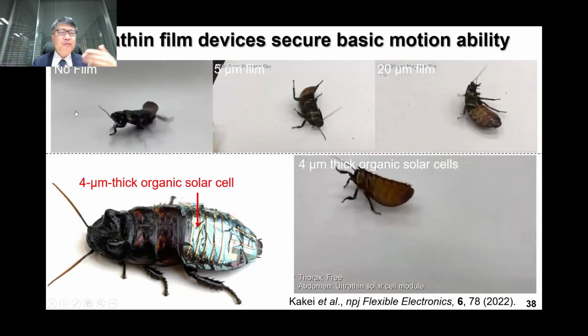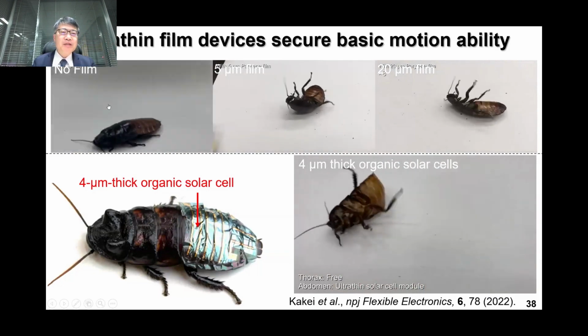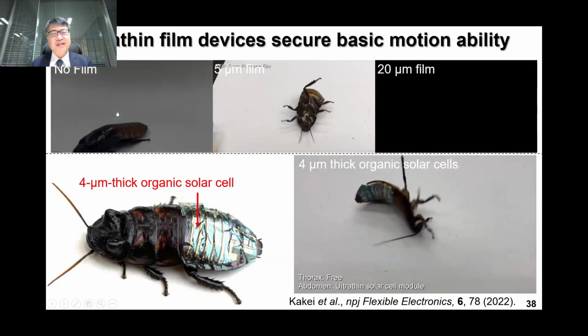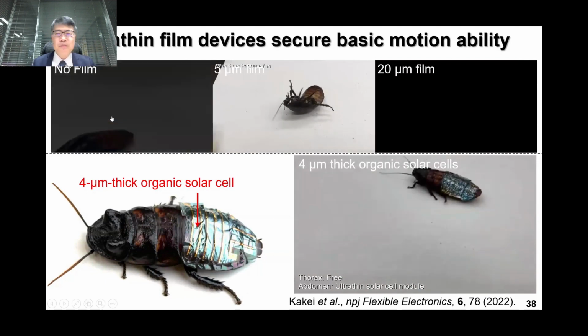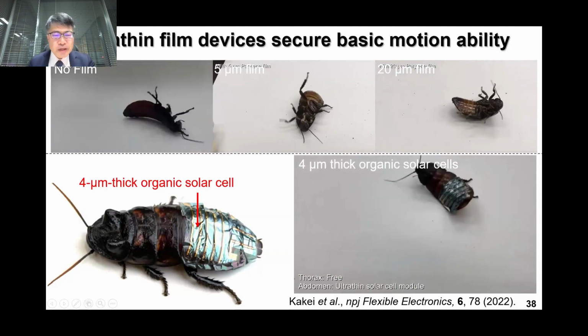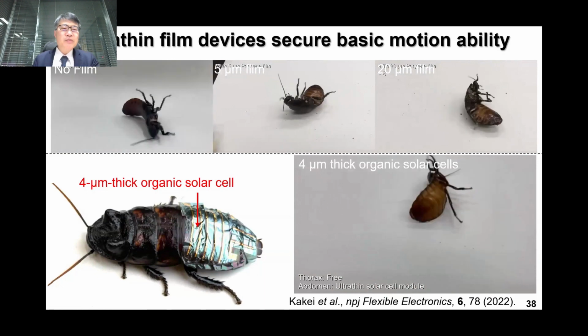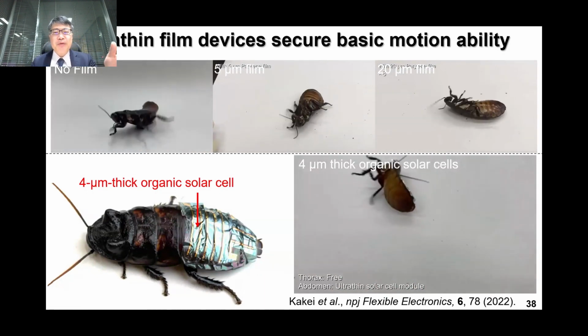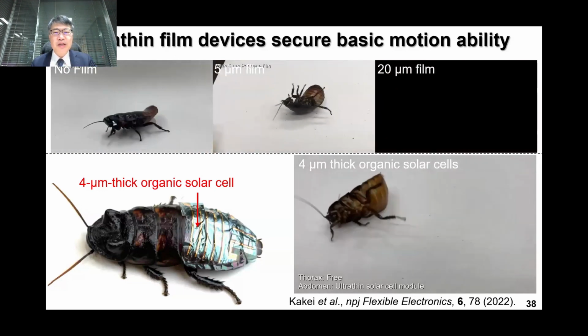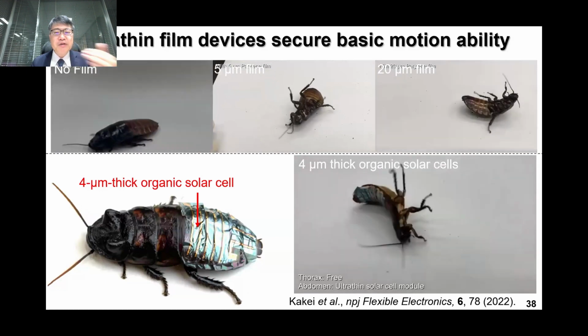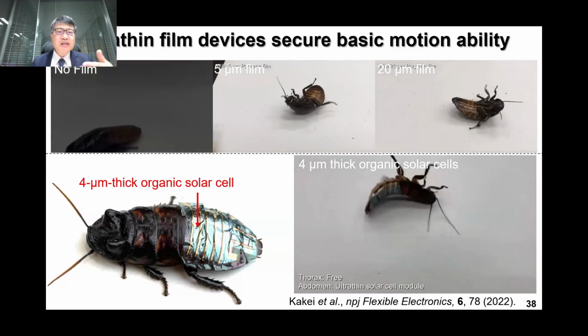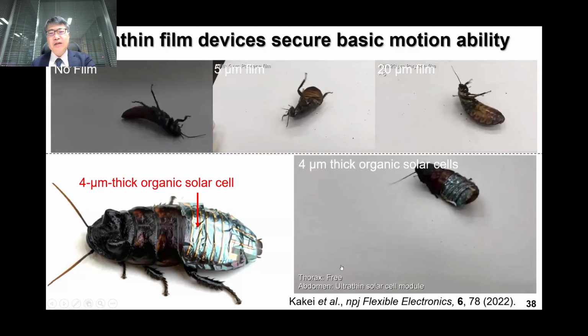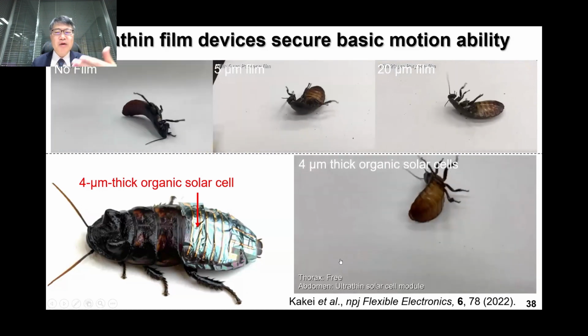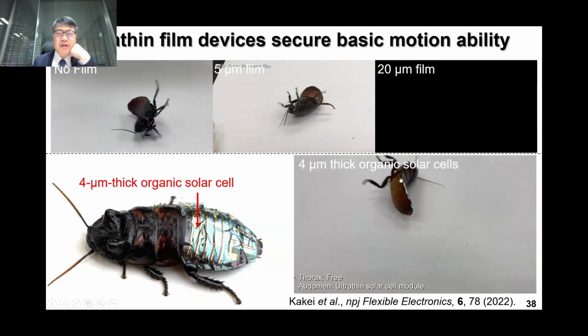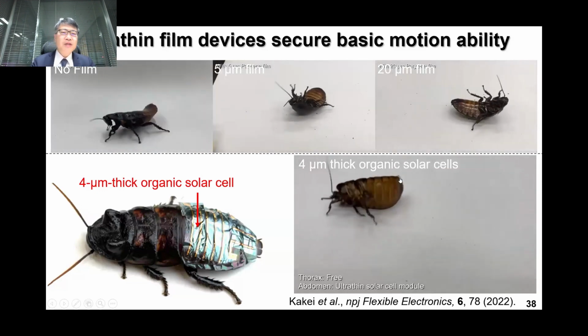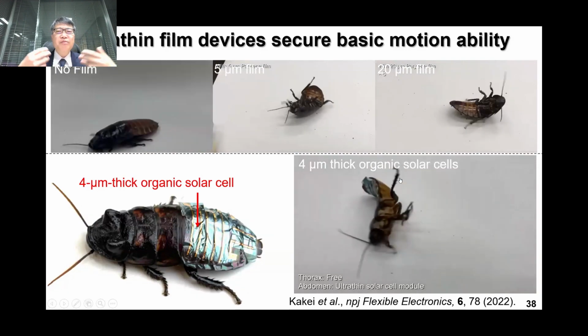Of course, when the insect is flipped without film, it's easy to return to the original position. However, when thin film devices are attached on the backside, that may prevent the natural motion. So we try to minimize such interference by reducing the thickness. When the thickness is less than 5 micron or maybe 4 micron, the insect can return to the normal position. But when it goes beyond 5 micron, the insect couldn't return. So in that way, we try to ensure the basic motion ability.